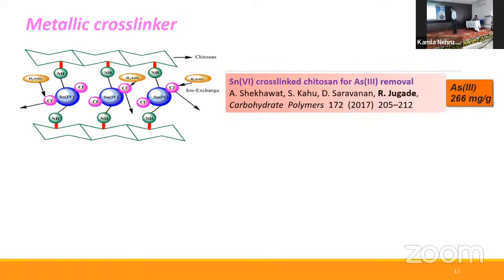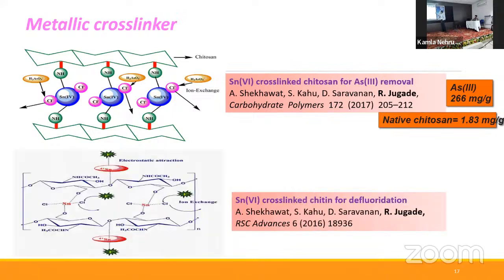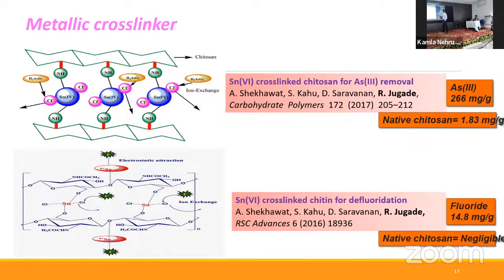We have used, or we were probably the first to use, the metallic cross-linkers like stannic chloride. SnCl4 was used as a cross-linking agent for removal of arsenic 3 from water, and the adsorption capacity for arsenic was found to be 266 milligrams per gram, whereas the native chitosan or the pure chitosan is having only 1.83 milligrams per gram. Similarly, we have carried out similar studies with fluoride. Now, chitosan has negligible adsorption capacity towards fluoride, but when we cross-linked with SnCl4, the fluoride adsorption capacity was found to improve from negligible to 14.8 milligrams per gram.